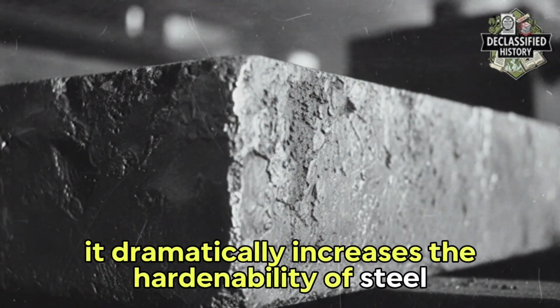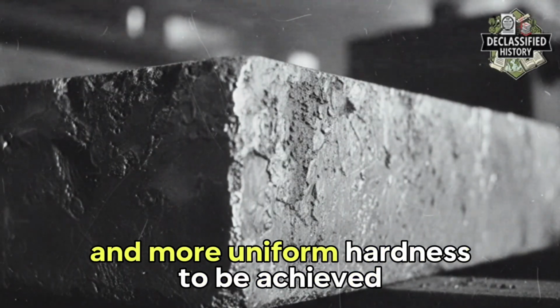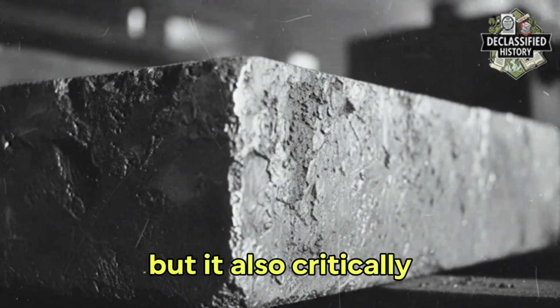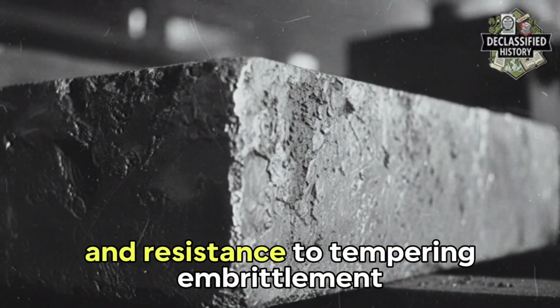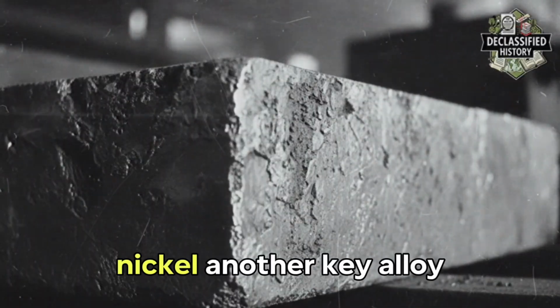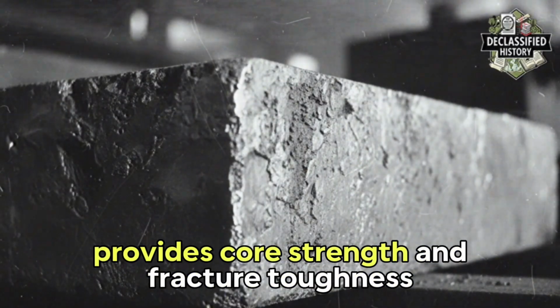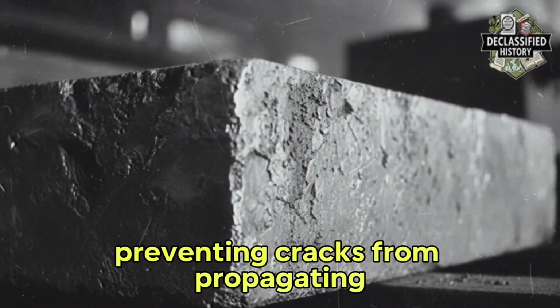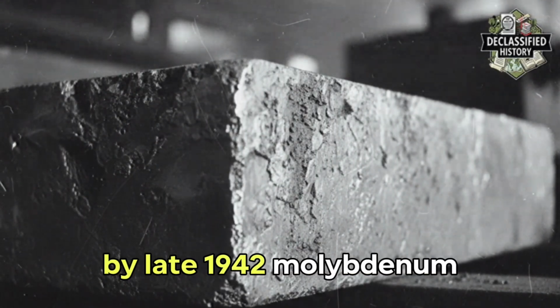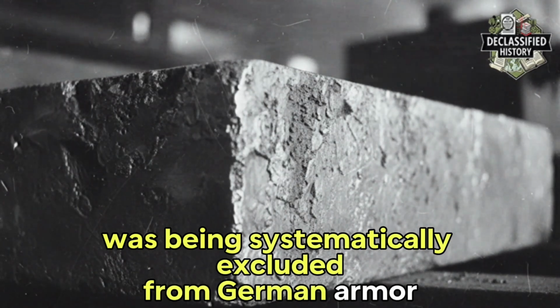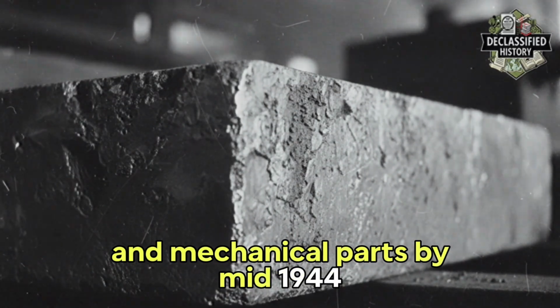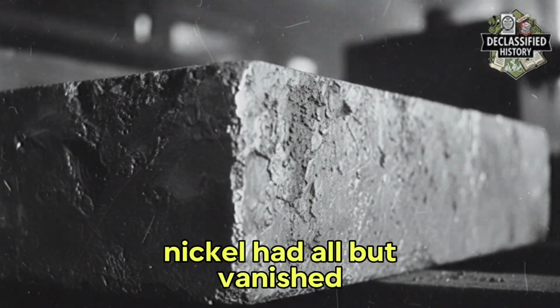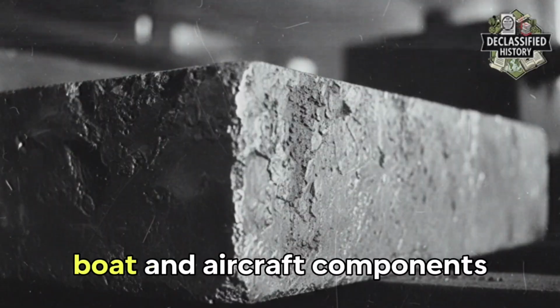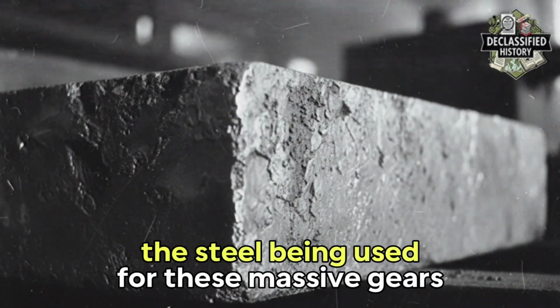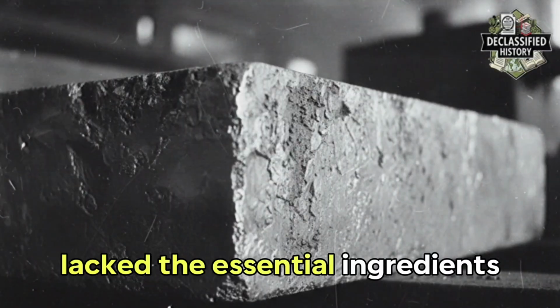Molybdenum is a miracle element. It dramatically increases the hardenability of steel, allowing a deeper and more uniform hardness to be achieved. But it also, critically, improves the steel's toughness and resistance to tempering embrittlement. Nickel, another key alloy, provides core strength and fracture toughness, preventing cracks from propagating. By late 1942, molybdenum was being systematically excluded from German armor and mechanical parts. By mid-1944, nickel had all but vanished, reserved for only the most critical U-boat and aircraft components. The steel being used for these massive gears lacked the essential ingredients.